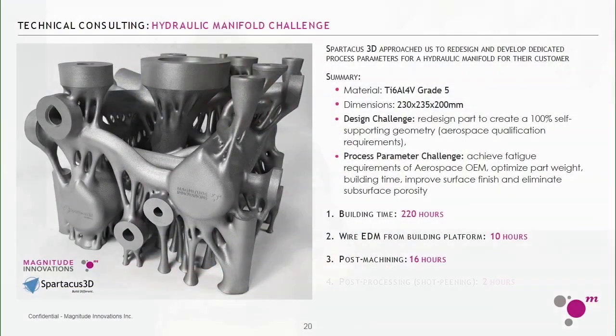So what we had is an application which is a hydraulic manifold. I can't talk about the final end user, but we did this with Spartacus 3D, where the application actually fits in a 250 by 250 build area. And of course, the first thing that we had as resistance is that titanium cracks. It's not possible to build something this big. Well, I think it is, and so we went ahead and did this.